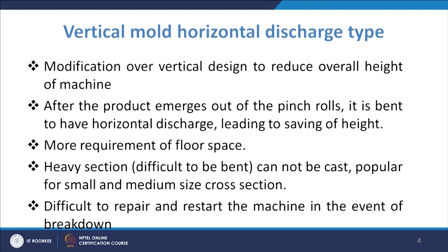The mould is vertical, but discharge is in the horizontal direction, so cutting will be done when the slab or billet is moving horizontally. In the earlier vertical type, you need vertical space — it comes down, you cut it, and then you proceed, requiring a very large space, and handling is certainly an issue. Whenever we feel that we should reduce the overall height or when handling is an issue, we go for this modification of the vertical type machine.